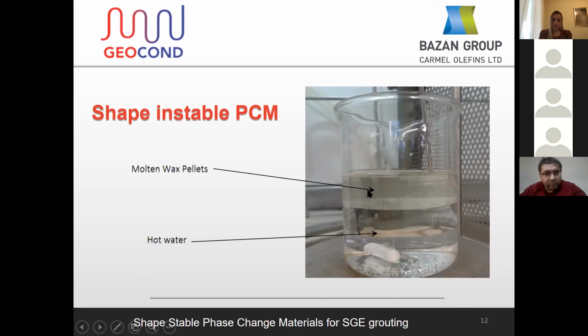At some point, finally, a layer of molten paraffin will form on the surface of the water. The viscosity of this molten paraffin is quite low, similar to that of vegetable oils. And using such material in technical applications is quite problematic because of its tendency to leak out.